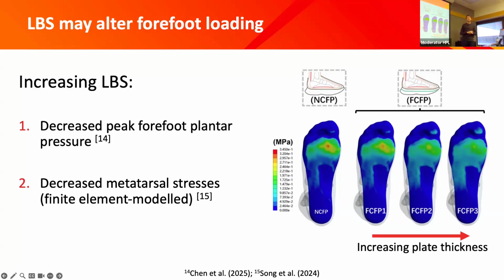The next three are all with the carbon fiber plate that was modeled inside the finite element model. And the carbon fiber plate, as we go to the right, is getting thicker and thicker. So you can already see, compared to the no carbon fiber plate condition, the first thinnest carbon fiber plate condition already has a reduction in that peak strain or stress happening under the metatarsal heads. And as that plate gets thicker in the model, those peak stresses get even lower. So although this is just a modeling study, it's very interesting to see that this could be a potential effect of increasing the longitudinal bending stiffness of a shoe.